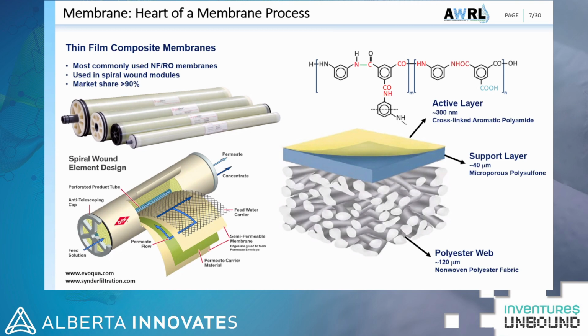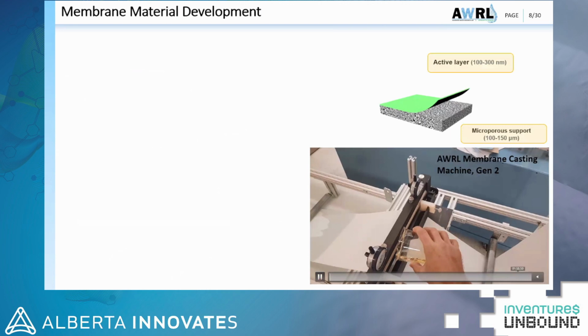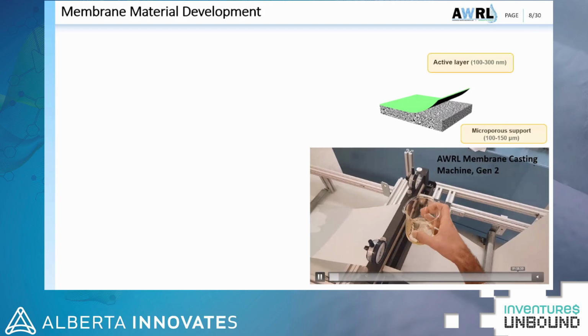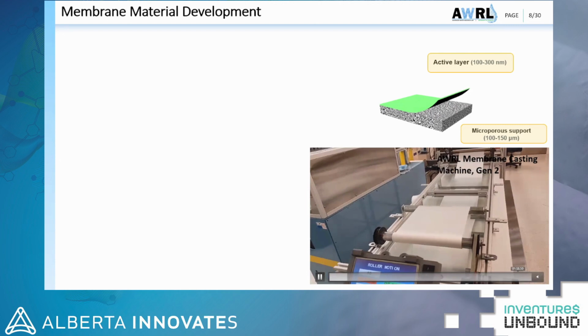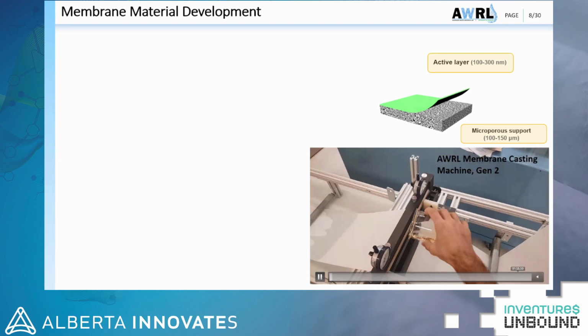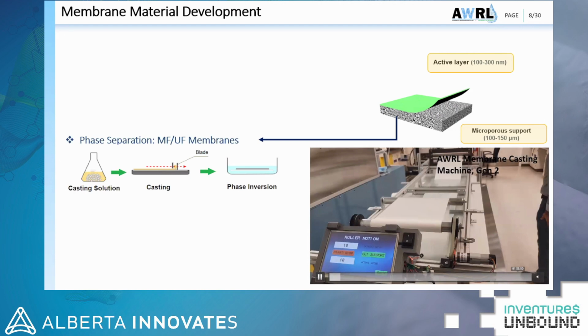In AWRL, we make the top and middle layers. Phase separation method is used to make the microfiltration and ultrafiltration membranes, which are also used as the middle layer of TFC reverse osmosis membrane. In the phase inversion method, polymer is cast on a suitable support and then placed in the water bath to form a thin layer of porous membrane.